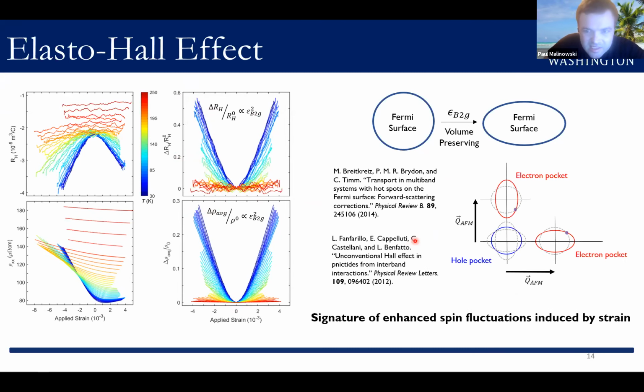So it turns out that there are previous theoretical works which actually provide a consistent explanation of our observations. And the upshot of these calculations is that in multiband systems like the iron pnictides, hotspots resulting from interband scattering from spin fluctuations can completely change the character of the minority carriers. So in this case, causing holes to behave like electrons. And this behavior drastically alters the transport coefficients, in particular leading to a large enhancement of the Hall coefficient as a function of increased spin fluctuation strength. So with these ideas in mind, we see that the large nonlinear Elasto-Hall effect that we observe can be interpreted as a transport signature of strain enhancing stripe-type spin fluctuations in this composition.